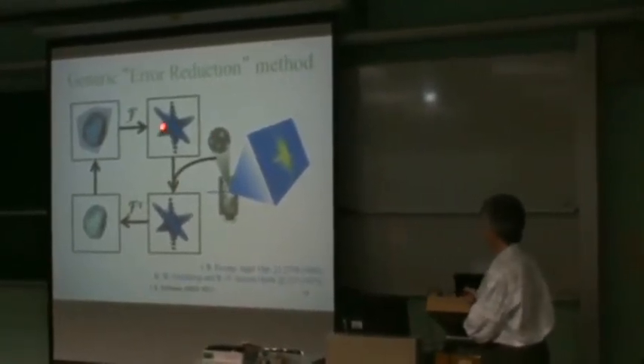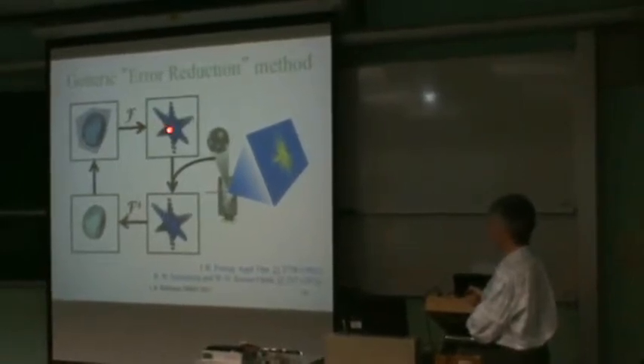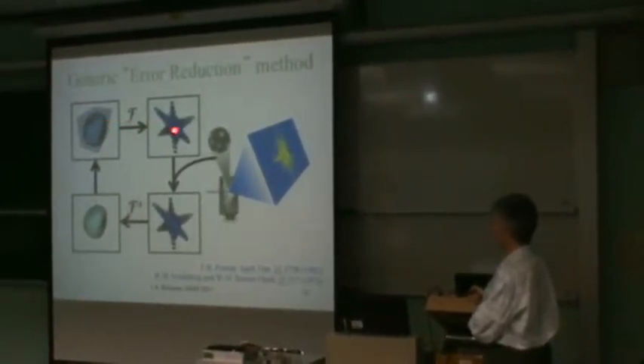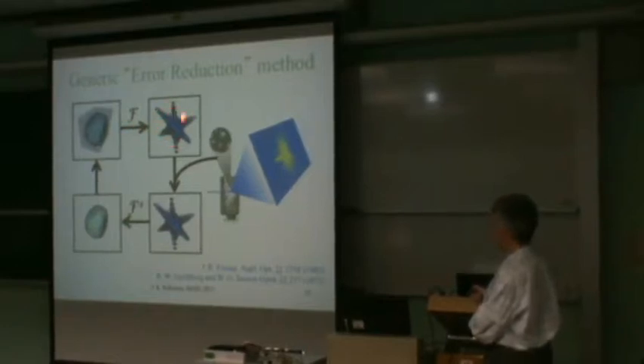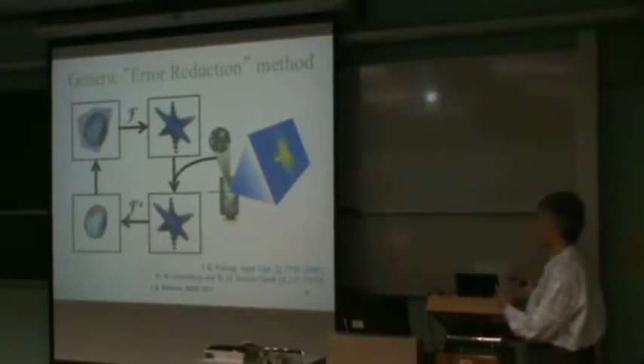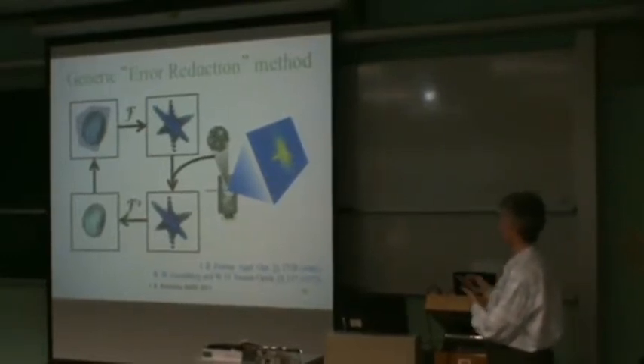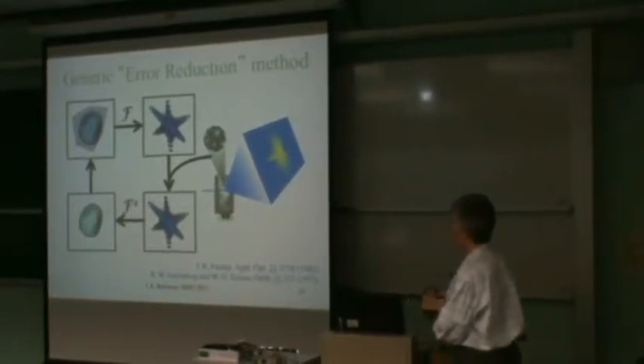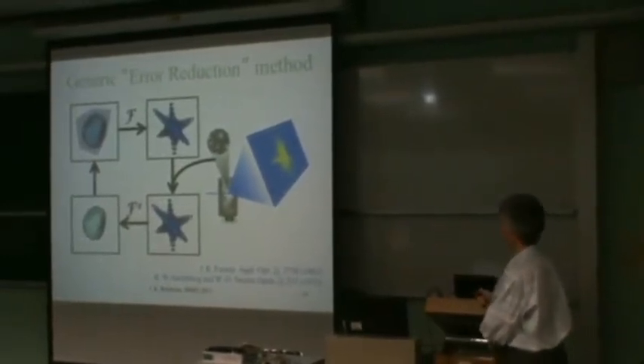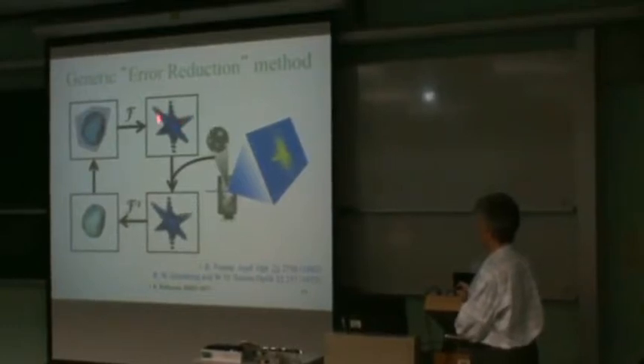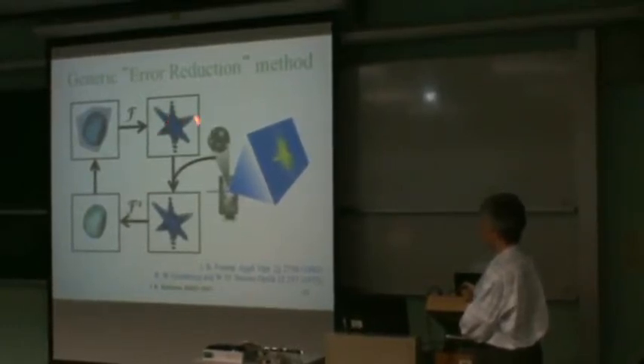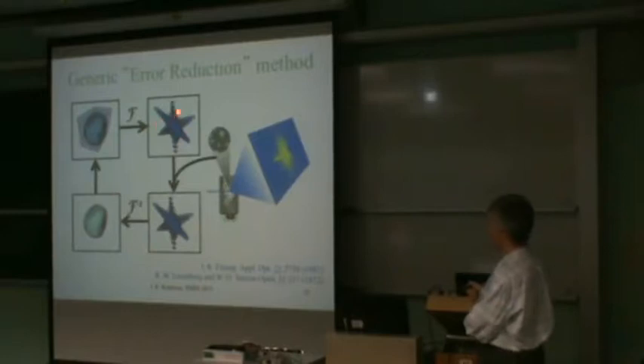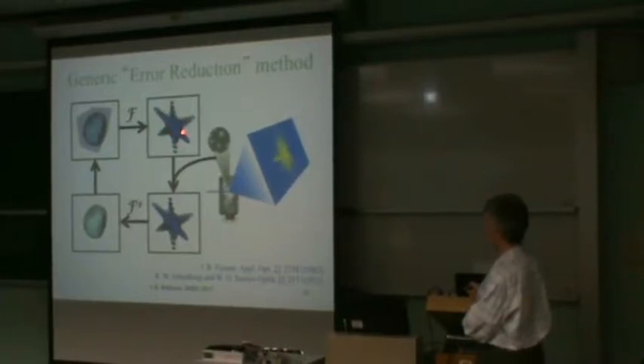And since it's a Fourier transform, you can just take the inverse Fourier transform, except for the not small problem that this is a complex function. You only measure the amplitude of it because you measure the intensity of the diffraction on the detector. You can't measure the phase of it, at least not easily. And so you have to use a bootstrap method to get the phase for the missing part of this diffraction pattern. But because you have additional information here, you've got more measurement points than you have information in the pattern.